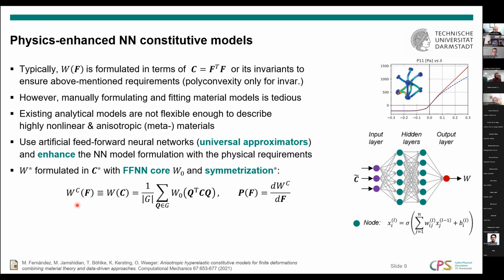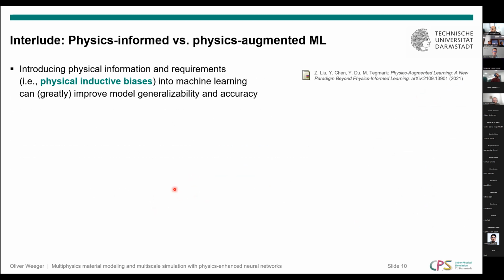So we formulate a strain energy function W in terms of the right Cauchy-Green tensor C, which is subject to this kind of weird symmetrization operation. And why we do this, I will explain in a minute. So we will say, and then this W naught over here, this would actually be the neural network. We do this kind of weird architecture because we want to enhance the model with the physical and the mathematical requirements. So in general, if you want to introduce physical information and requirements, a so-called inductive bias from physical requirements into machine learning, it will greatly improve the model generalizability and also in many cases the accuracy.